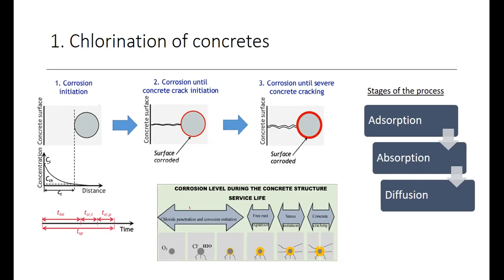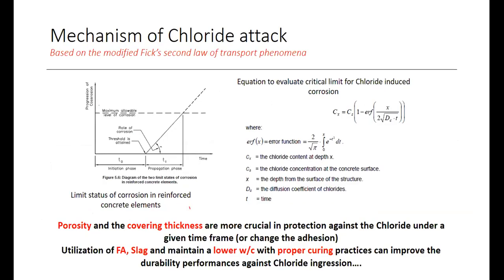The cracking means there will be more openings, so more chloride ions can penetrate, and then a severe corrosion process will occur inside the concrete. It's like a vicious circle. There are a lot of mechanisms that have been developed. I have taken one which was developed basically with Fick's second law of transport phenomena, a very familiar equation for chemical engineers, I suppose.